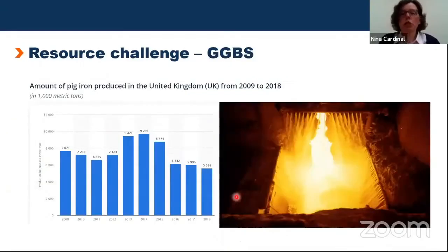With regards to GGBS, GGBS is a byproduct of the iron-making process. You see here on the right-hand side a photo where the slag from a blast furnace is quenched by water. The quenching is required so that we get from the slag later the right properties for ground granulated blast furnace slag. If you look here, however, on this chart is the production of iron in the UK from 2009 to